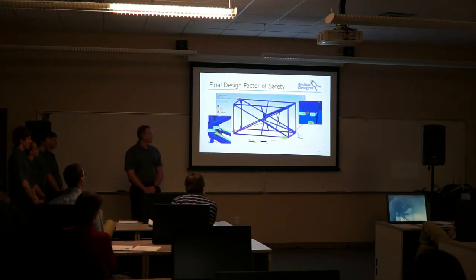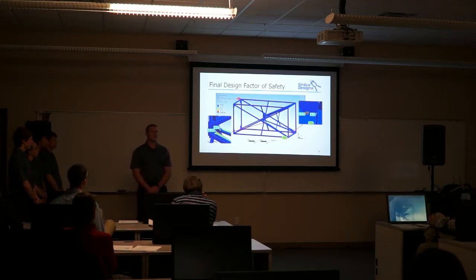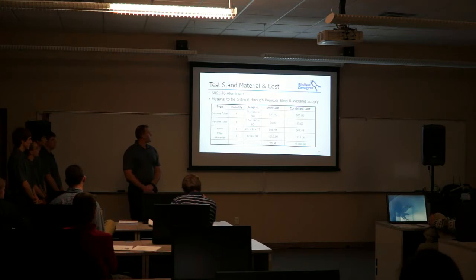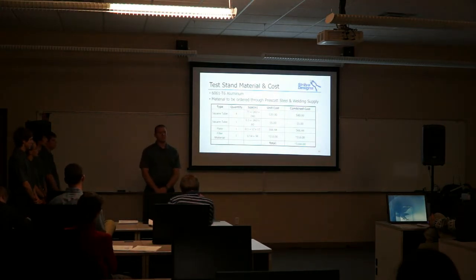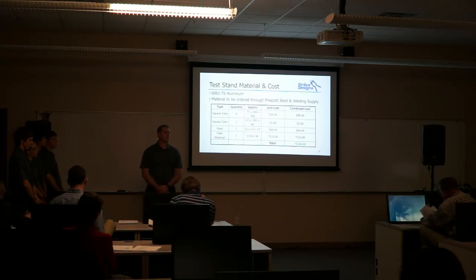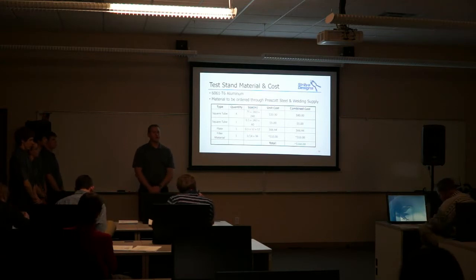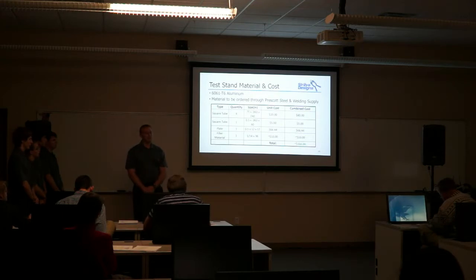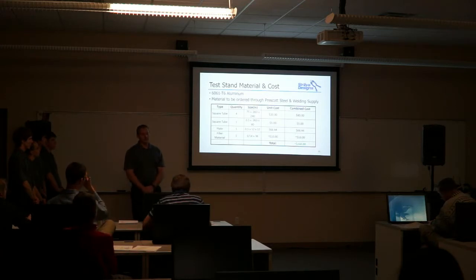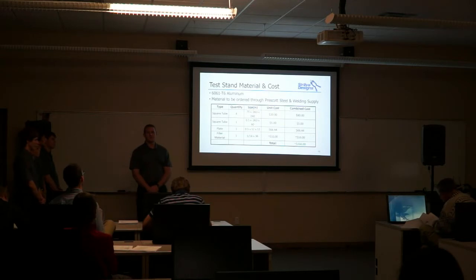The ANSYS analysis of this showed that the stress was significantly reduced and deformation was reduced to approximately 6/1000 of an inch at a 2,500 pound load. The stress concentrations were also significantly reduced, and the lowest factor of safety of the entire stand was approximately 6. The 6061 T6 aluminum was selected over steel due to its low weight, high corrosion resistance, and low cost. The material is planned to be ordered from Prescott Steel, as it is readily available there.